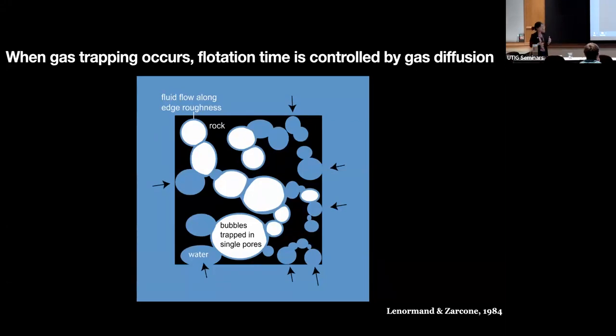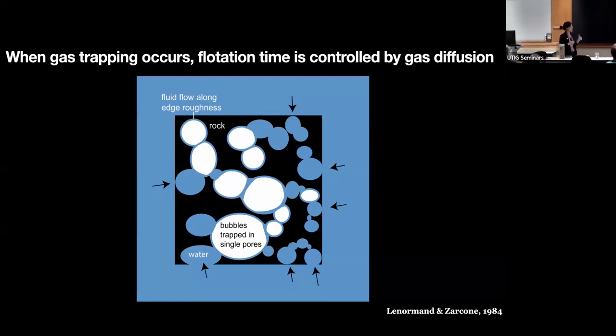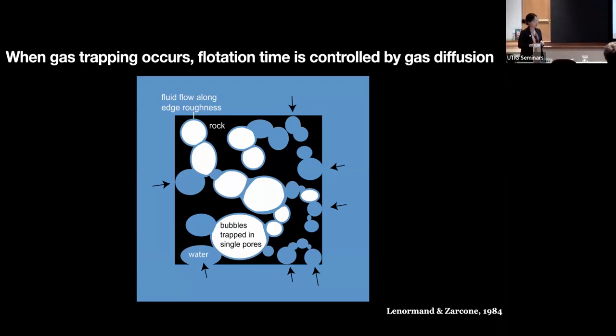But now the time scale controls the flotation. For all the pores to be 100% filled, it depends on how long it takes the gas inside these bubbles with trapped liquid to go out, okay? That's the time scale that controls that. This doesn't happen all the time, because only when capillary force dominates the scenario would you get this kind of gas trapping.